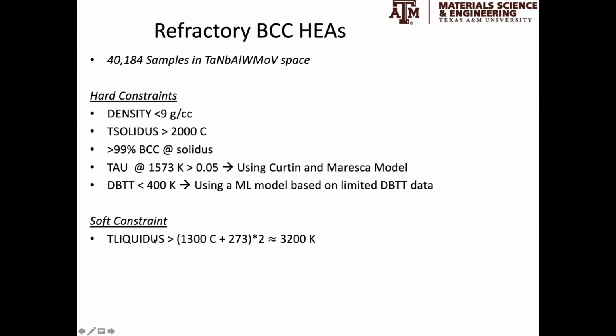And of course, if we want a material that withstands high temperatures for long times, we want materials that undergo the least creep possible. As a rule of thumb, that means the operating temperature, for example 1300 Celsius, should be about half of the homologous temperature. So we'll be looking for alloys that have a very high liquidus temperature.